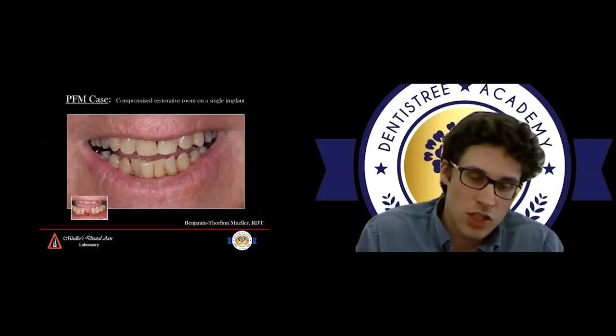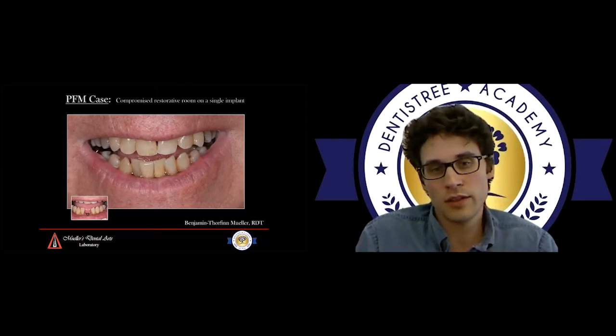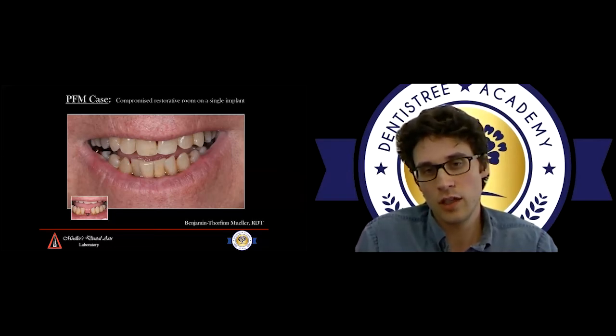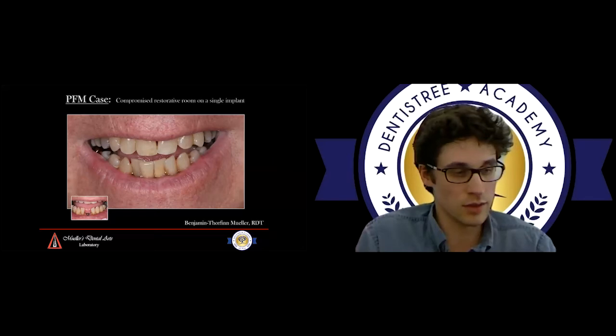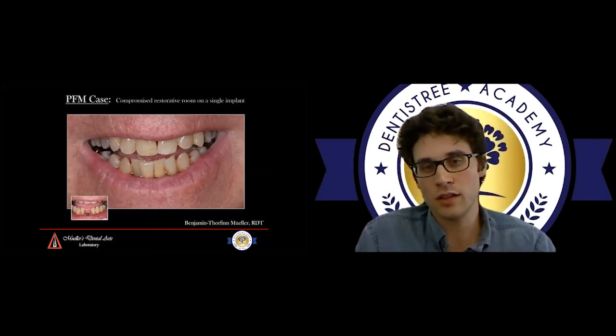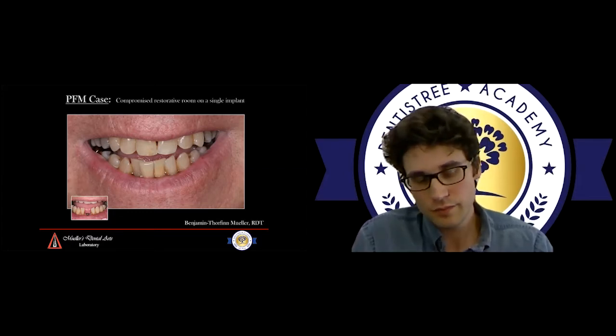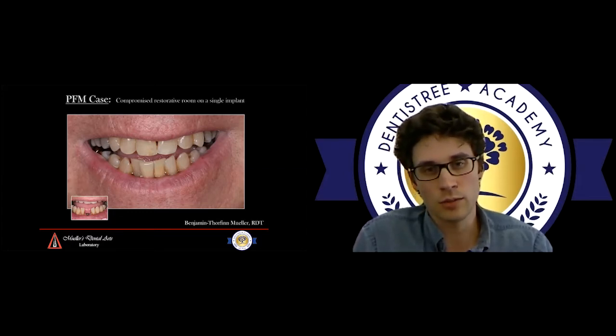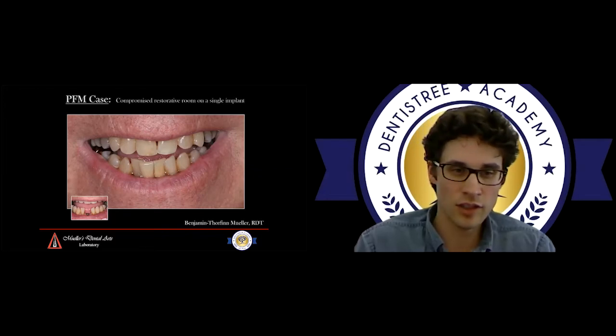Here's another PFM case — a good application. This is a compromised case; lower teeth are always challenging because they're so small. This implant was placed right in the center, which was great, but because everything is so small and tiny, if one had made a zirconia framework around a Ti-base or a custom abutment, the zirconia or lithium silicate would have become very thin, leading to future breaking of the case. We did a nice metal ceramic framework — a metal framework of high noble alloy — layered it, and this patient is doing great long-term.